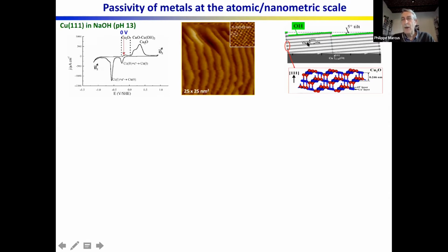From this, we can derive a model of the surface oxide layer, which is shown here. And we can show that the oxide which is formed is very highly crystallized. It grows in a direction that is governed by the structure of the base surface. And also the oxide is covered by a layer of hydroxyl ions. And this points to the important effect of interface energy, which is minimized by this direction of growth, and the surface energy, which is minimized by the adsorption of OH. So crystallinity, minimization of interface and surface energies are keys to understand passivity.